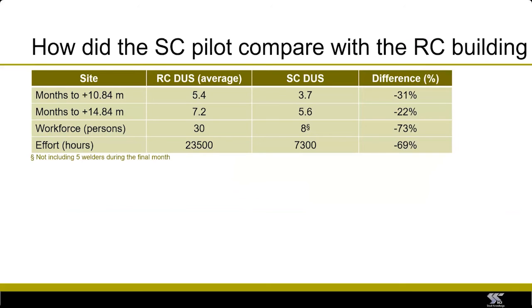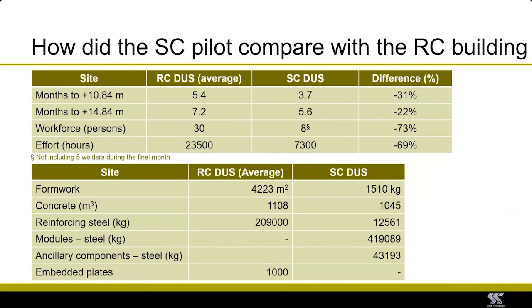In terms of workforce, on a typical reinforced concrete project, there were 30 people working on site. In the case of this demonstration project, we had 8 people working on site, plus 5 welders who were there for 1 month when we were welding the top 2 levels of the building. So a reduction of 73% in workforce. And in terms of number of hours worked on site, there was a reduction from 23,500 hours to 7,300 hours, a reduction of just under 70%.